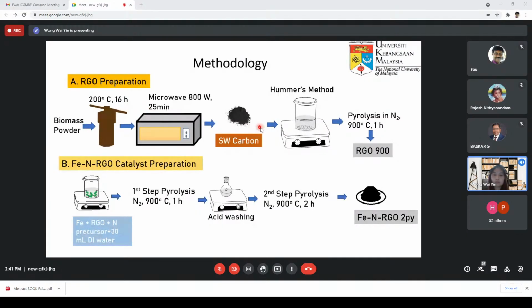Then it undergoes Hummers' method, with the intention to create more defective sites on the layers in the carbon of the biomass itself. So we create the oxygen functional groups. It's basically oxidation. We oxidize it to try to create and exfoliate the layers. Then we undergo the pyrolysis of this material under an inert environment. From this process, the volatiles will be removed, and also all the oxides will be reduced. So that will create reduced graphene oxide.